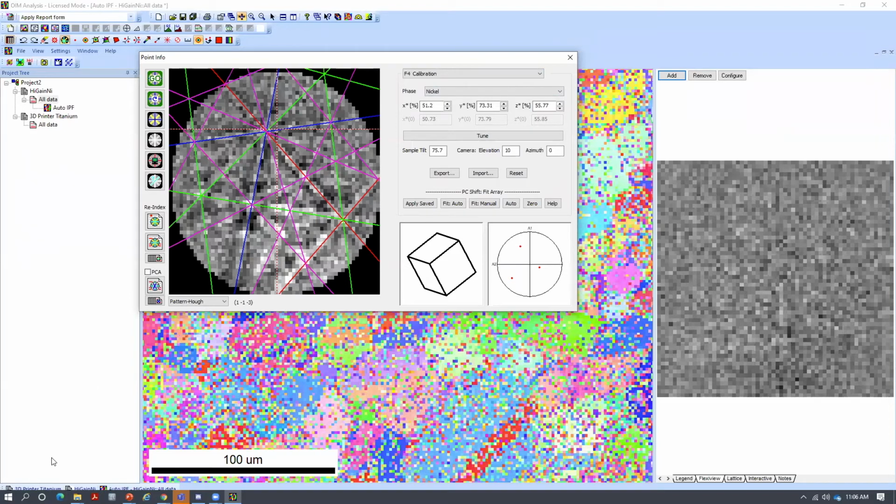So again, we talked a little about this yesterday. When you mount a sample, you have your stage at 70-degree tilt. Then you have your pin stub in there, and then you have your sticky material, and then you have your mount. There's a lot of wiggle room built up into that system, which means your actual angle may not be what you think it is. It might not be that 70 degrees. It may be 71 or 72 or maybe 69 or 68. That can be seen in your data. So here's where I can go in and tune for this, and it'll make this pattern fit better. This is a kind of secondary calibration I can do to correct issues from the actual system itself.